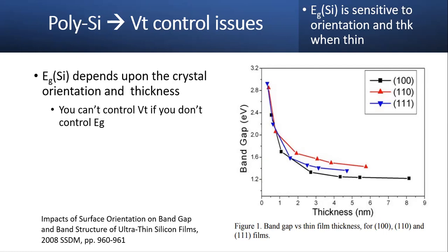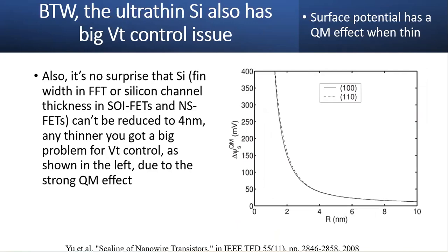Right? If your VT control has to be within a couple hundred millivolts, like 10 millivolts, then you cannot do it. If your VT is like 10 volts, then you're fine, right? If you can pull up with the mobility degradations. By the way, the ultra thin silicon has a VT control issue.